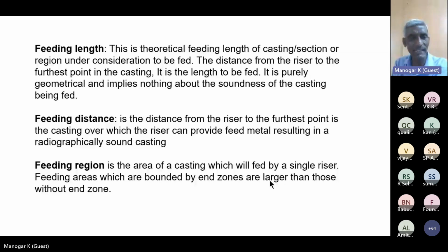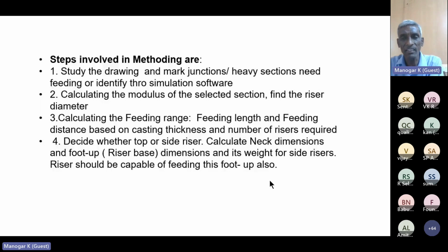Steps and method: study the drawing and mark junctions. Sections needing feeding are identified through simulation software. Calculate the modulus of the selected section and find the riser diameter. Calculate the feeding range, feeding length and feeding distance based on the casting thickness. Decide whether top or side riser. Calculate the neck dimensions and foot-up if it is a side riser, and the riser should be capable of feeding the foot-up weight also.